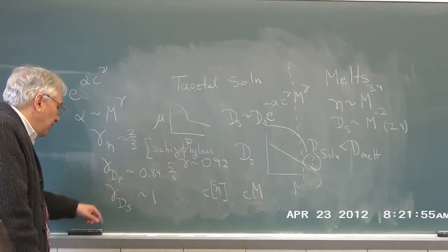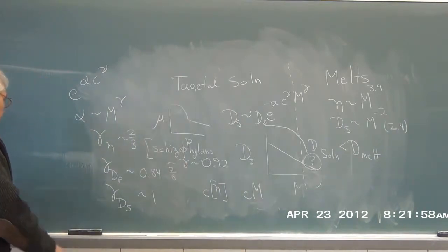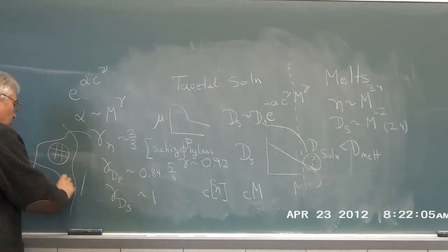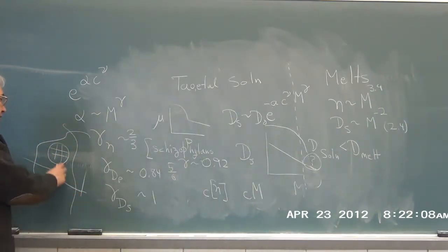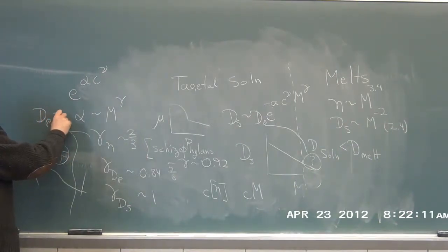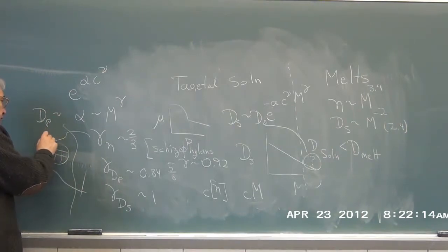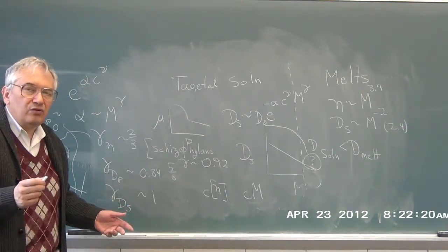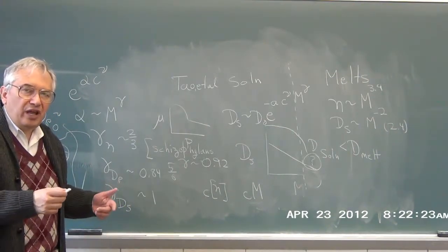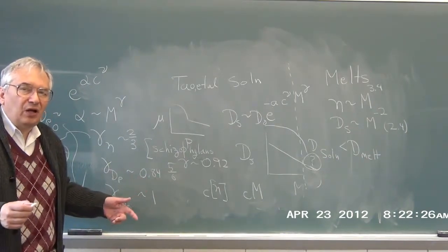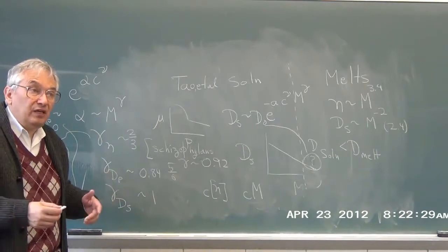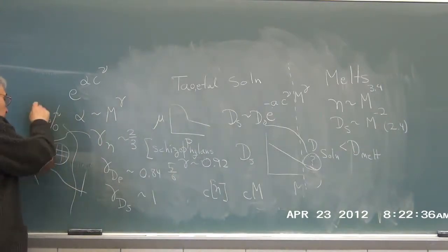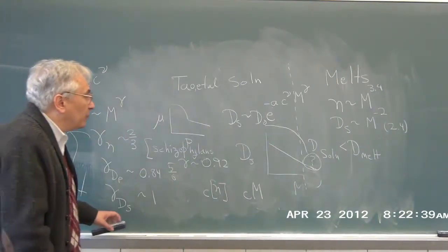This last bit already has an implication, namely there are people who will model probe diffusion, and here is the probe, and here is a very large polymer, and there are models that propose that dP is proportional, for very large chains and high concentration, to m to the 0. And the reason is the probe is almost never close to a chain end. It's just close to a chain middle, and therefore it can't see how big the polymer molecular weight is, and thus d must be independent of polymer molecular weight. Well, those models are conclusively rejected by experiment. There's no doubt about that.